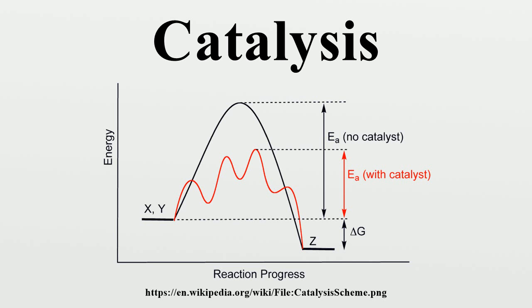As an example of a detailed mechanism at the microscopic level, in 2008 Danish researchers first revealed the sequence of events when oxygen and hydrogen combine on the surface of titanium dioxide to produce water. With a time-lapse series of scanning tunneling microscopy images, they determined the molecules undergo adsorption, dissociation and diffusion before reacting. The intermediate reaction states were HO2, H2O2, then H3O2, and the final reaction product, after which the water molecule desorbs from the catalyst surface.